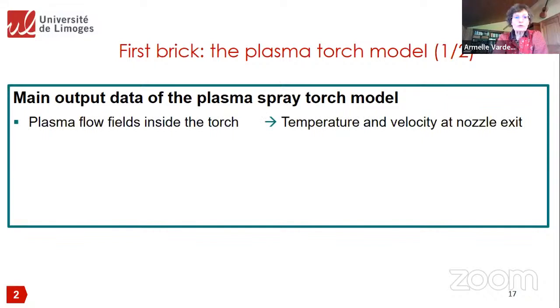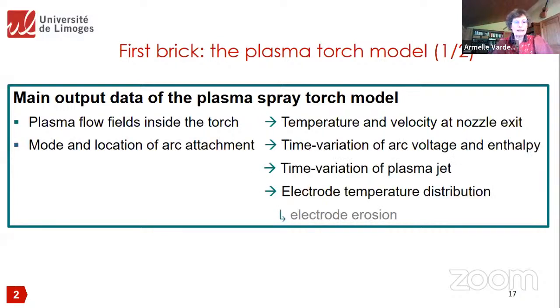First, of course, the plasma flow field inside the torch, that is plasma velocity and plasma temperature. And you also need to have this temperature and velocity at the nozzle exit, something which is also very important. And it's the second main important prediction of the plasma torch model: where the arc will attach and how it will attach.